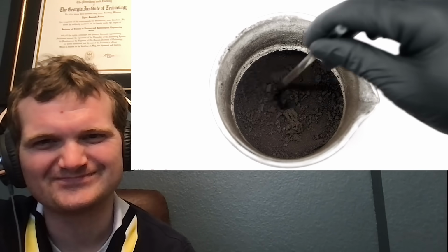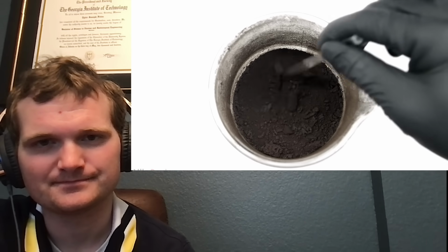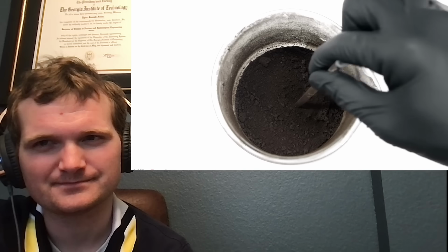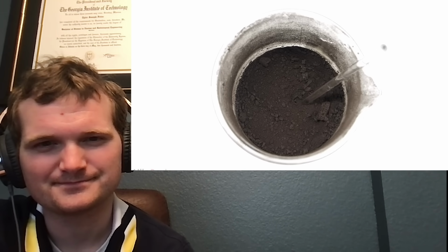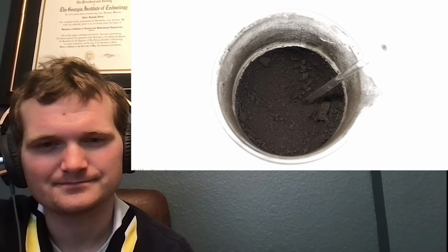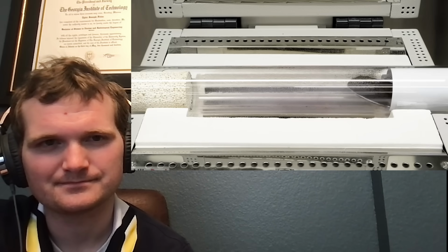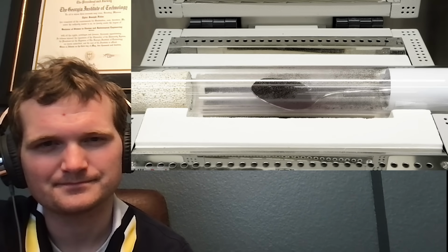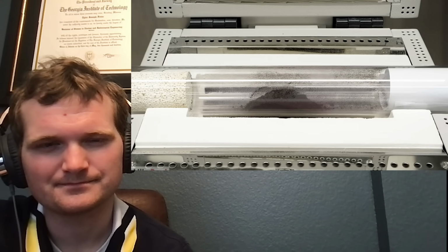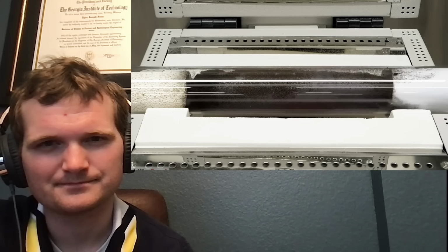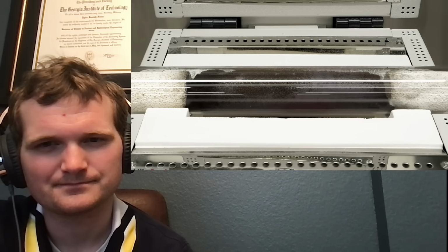Okay, so this first run turned out to be way more successful than I expected. The pellet that I had made, though, was kind of ugly, and I still had a bunch of oxide powder. The next thing that I wanted to do was use the rest of it and make several, hopefully nicer pellets. To do this, I figured I had to just more or less repeat the exact same process. This time, I felt that it was probably fine to fill the tube a lot more, and I added about 10 times the amount. However, this was only about 70% of the powder that I had left, so after this, I would still have to do one other run.